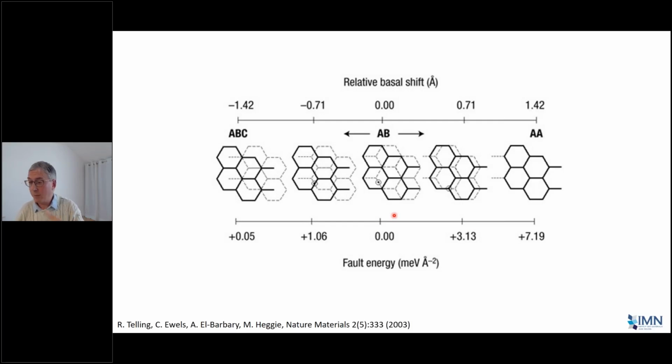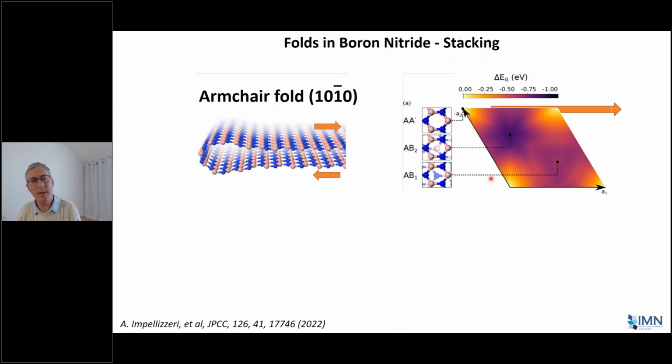So instead, I'm going to switch materials and talk about another material a bit like graphene. It's called boron nitride. So each one of these corners is an atom, and it was carbon. Now it's going to be boron, then nitrogen, boron, then nitrogen, alternating. And this is boron nitride. And unlike graphene, this is a material which has a very wide gap. So this is a strong insulating material, and it ideally likes to be in this AA prime stacking. So alternate layers on top of each other have a boron above a nitrogen, above a boron, above a nitrogen, because they're highly charged, positive and negative. So they like to stack in alternation.